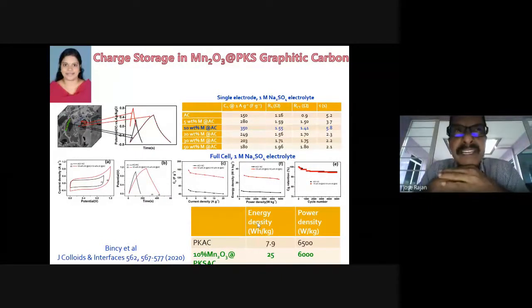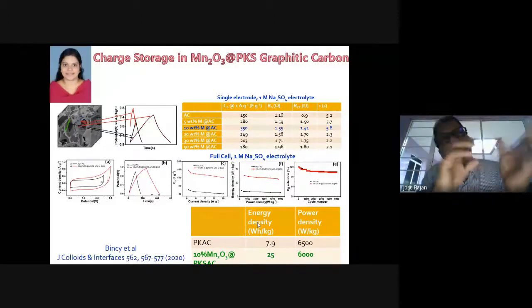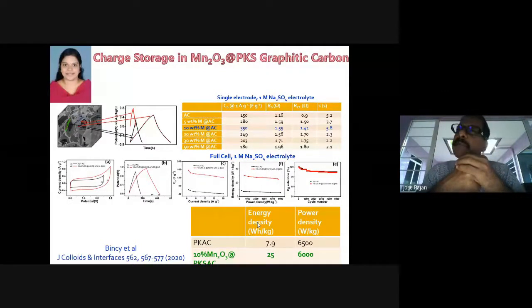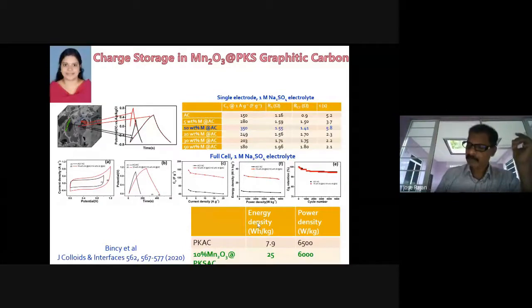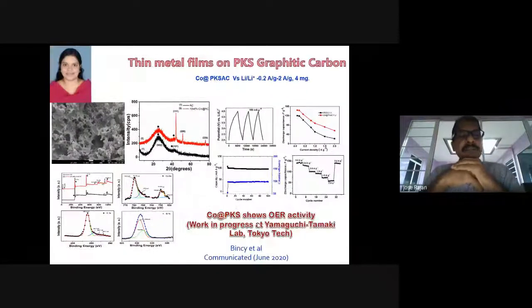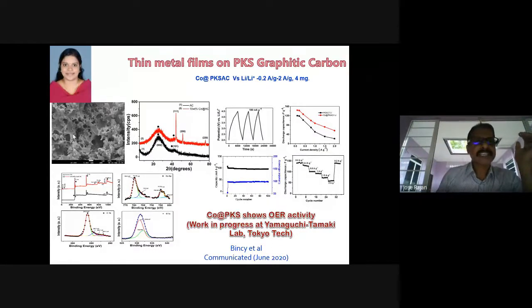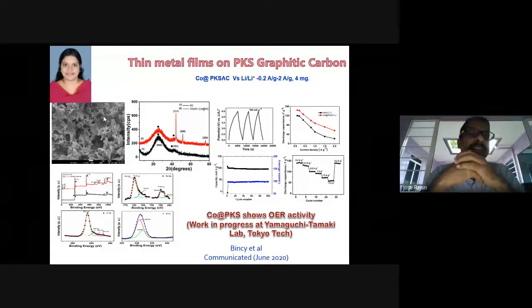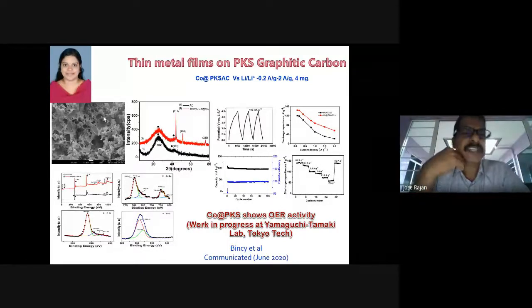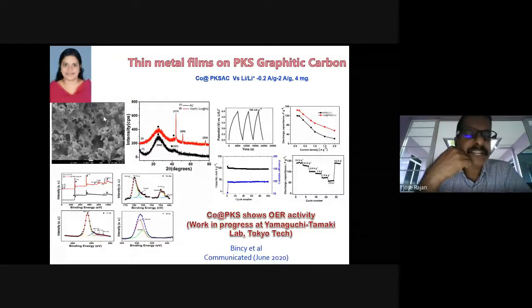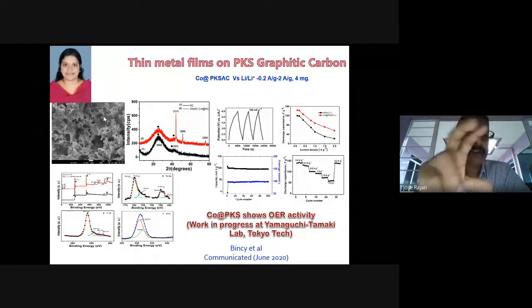Again, metal is inevitable, because metals offer much superior properties than bio or renewable materials. So how to functionalize these renewable materials with a minimum quantity of earth-borne materials has been our focus. In the next work, we did the same, but instead of metal oxide, here we coated a metallic film on porous carbon. This was also done by Bincy. You would see the SEM shown here. That is the microstructure of carbon containing a thin film of cobalt on its surface.